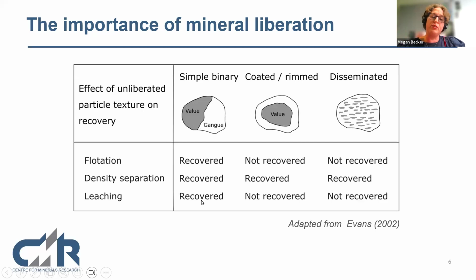And again, if you're preparing your material for leaching, this texture, your lixiviant should be able to see it. That one, your lixiviant has no access to the valuable unless you've used some form of grinding where you've created cracks. So potentially some sort of compression grinding that creates a crack network that your lixiviant could access the valuable. If that is the case, then that might be recovered. But as it stands, it's unlikely to be recovered, and that wouldn't be recovered. So it's actually very important for us to understand the texture, because all these particles have the same liberation, but they will behave differently in different separation processes.